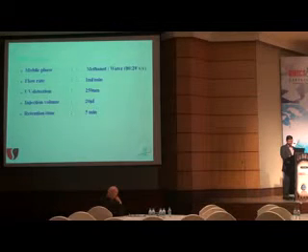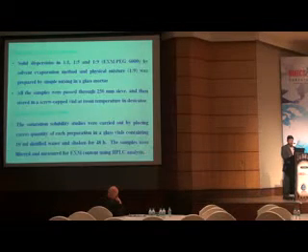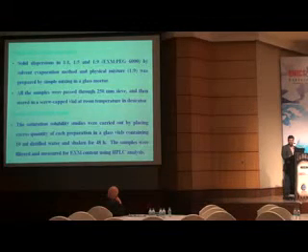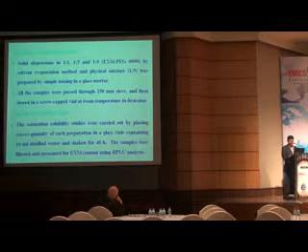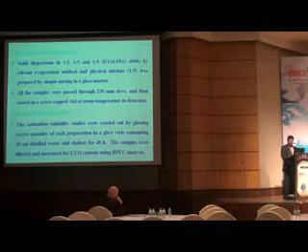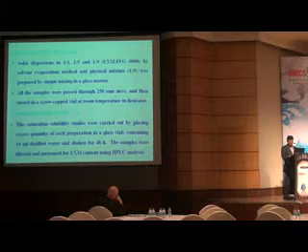And this was the HPLC analytical method we used: the mobile phase constituting methanol and water in 80 to 20 parts, a flow rate of 1 ml per minute, UV detection at 250 nanometers, and injection volume of 20 microliters. Then after conducting the phase solubility studies, we have seen that PEG 6000 has shown a better solubility profile with a linear increase, so we have taken PEG 6000 as a carrier to